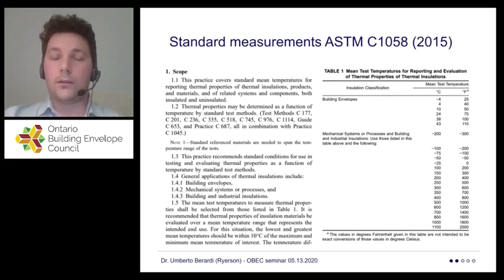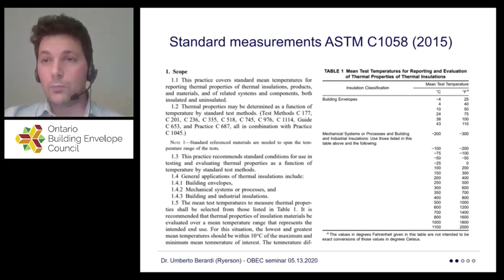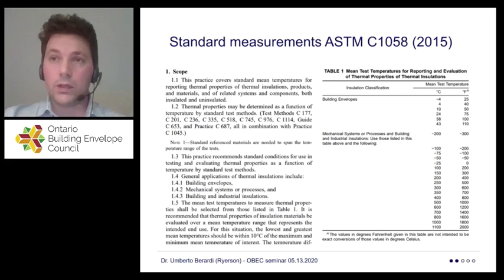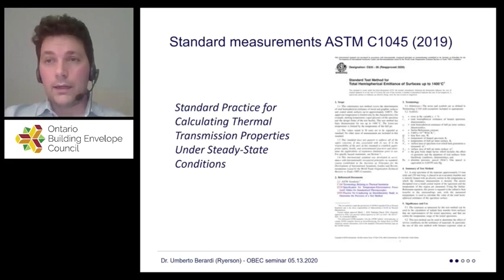Clearly, to be honest, a lot of companies do not find interest in doing this kind of extra measurement. On one side, because often the software we use has no interest or capability to account for the dependence of thermal conductivity on temperature, but also because the tests tend to be quite expensive, and nobody wants to start doing a lot of tests unless everybody does those tests. And so far, there is a general approach where doing the tests at only 20 Celsius is good enough to populate a technical sheet, to give a value to the industry, and the industry will start moving from there. So in reality, this is not necessarily the best approach, but it's been quite common, especially until recently, when this kind of test was quite expensive. And now these tests at different temperatures are getting more and more available across the globe.